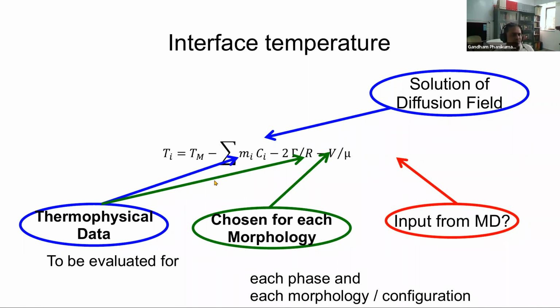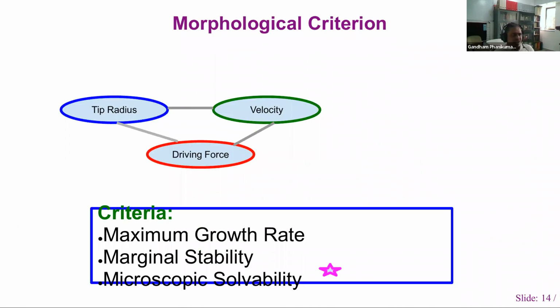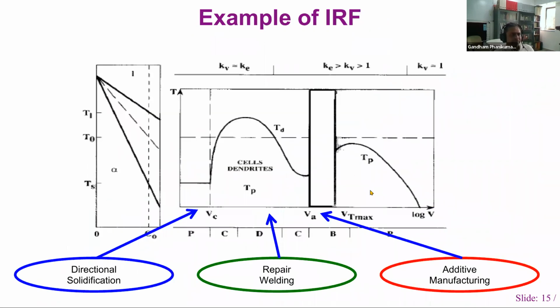So in other words, all of these can be calculated, and you can find out what is the Ti, and that is nothing but the interface response function. And that, when combined with the process parameters like velocity, can give you a lot of information about the driving force for solidification. So here is some map like that.